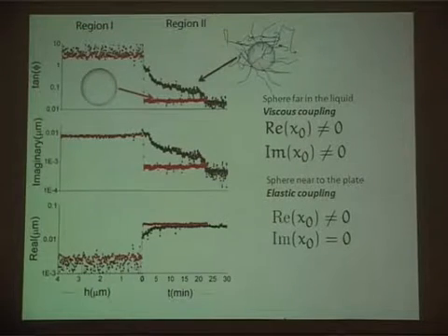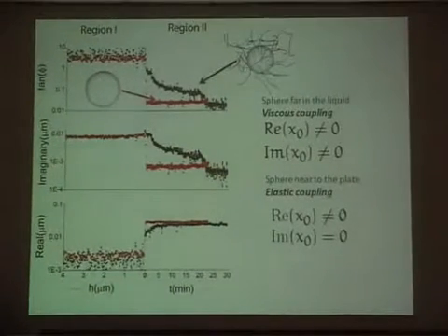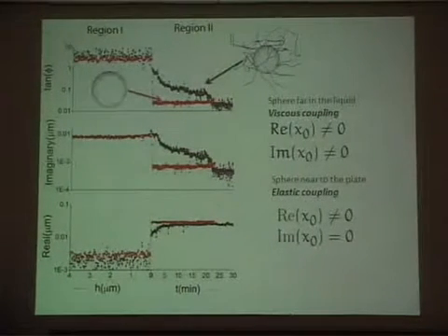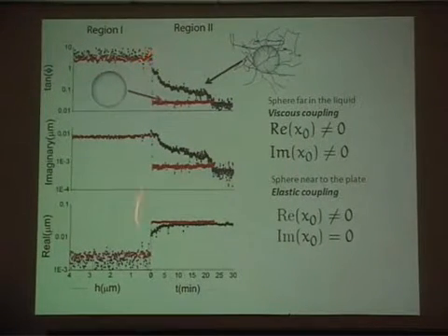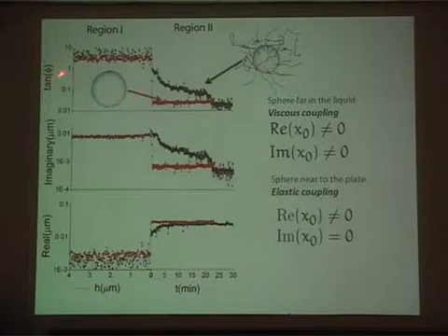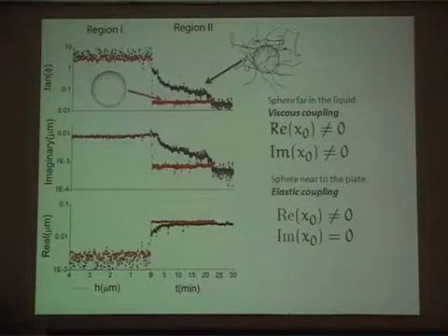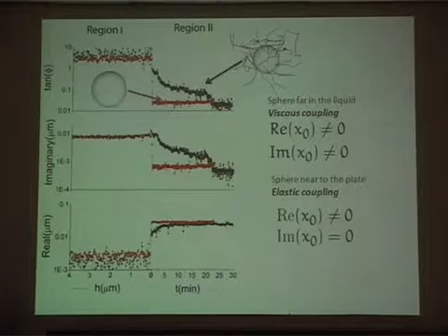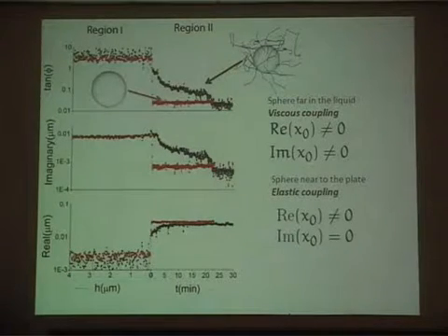Once I have a hard particle, the particle is up here. The tan phi is a measure of how well the particle has got stuck. If I take a silica particle, the moment it comes to the plate, boom, the phi goes down. It says that the particle has got stuck almost immediately. If I take a polystyrene particle which has hairs on top of it, then there is a lot of time involved in the whole thing.